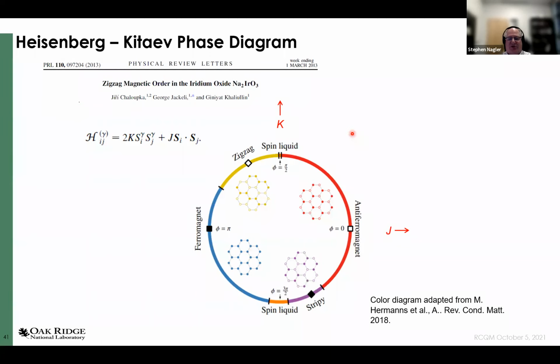Okay, in this simple Hamiltonian, the ground states include all 4 of the possible collinear structures for a honeycomb lattice in 2 dimensions. So you see here, if J positive is antiferromagnetic in this case, and if that's dominant, you will get an antiferromagnetic lattice where the dark circles are spin up and the light circles are spin down.